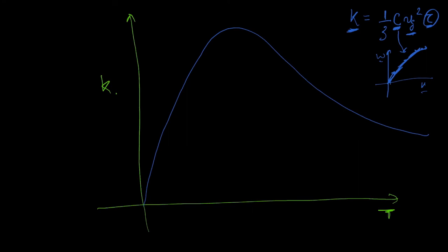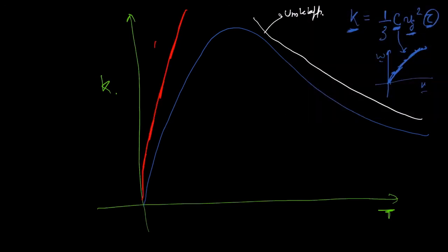Okay, so this is pretty much made of three parts. In the high temperature regime, the Umklapp process dominates, which we just talked about. And in the low temperature regions, boundary and impurity scattering dominates. This shape comes if there was only boundary and impurity scattering; it would become constant. So let me draw again on a different slide.